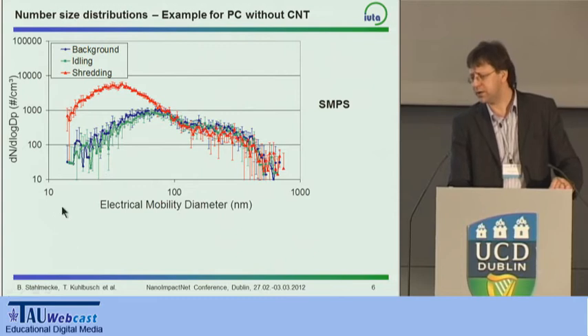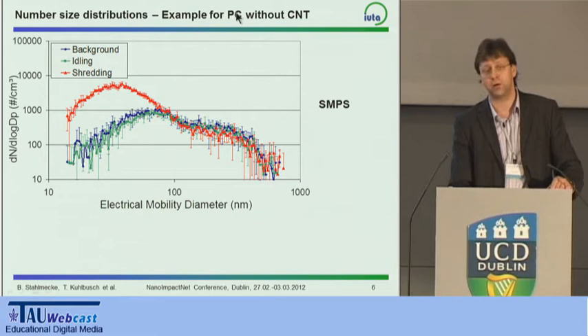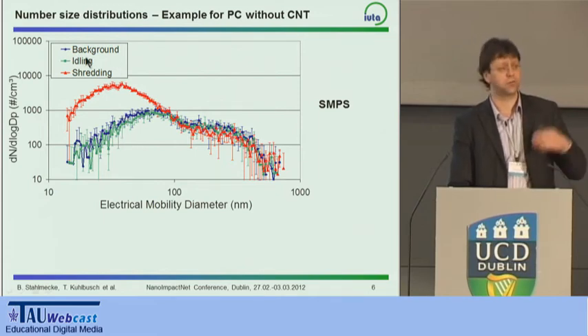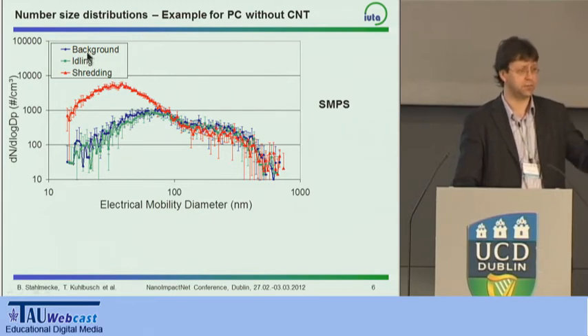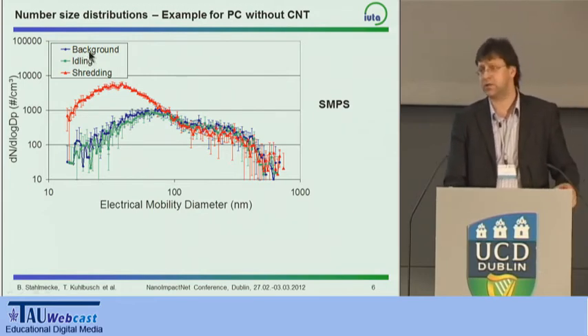What you see here is the size range and the number concentration, and we have the background concentration in blue. Then we have the idling of the shredding machine, giving pretty much the same size distribution, but as soon as the shredding starts, here polycarbonate without any carbon nanotubes added, you see an additional peak between about 40 and 80 nanometers of particles actually emitted by the shredding process itself. What we set as background is the idling, which means running the machine without any shredding activity, but still turning the disk.